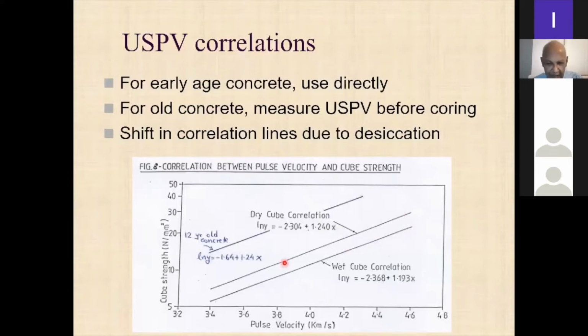Separately in the lab, we also got a dry cube correlation like this. Now we got some pulse velocity and core test results from the structure. So what we did is, in order to get this correlation line for the structure, well, those days we did not take, now you are supposed to take 18 cores to get this correlation. Those days we would have taken maybe about 8 or 10 cores. So you have 8 or 10 strength readings and 8 or 10 pulse velocity readings. Now actually you can draw y equals mx plus c through that, but here we are maintaining this m the same as this m in order to make this parallel shift.